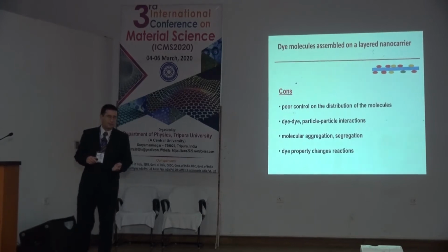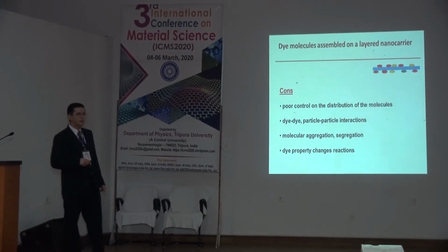Of course, there are some disadvantages. Poor control of the distribution of the molecules. You can fix the position of the dye, maybe the orientation between each other, but this is the problem. Dye aggregation, so dye-dye, particle-particle interaction, can significantly affect photophysical properties. A type of dye would segregate on the host at a different place than the other type of dye. Dye properties can change. This is sometimes an advantage, as Peter Bohat showed last time in his lecture, but sometimes we observe negative effects.